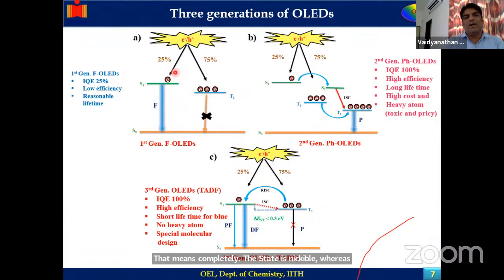That means only one-fourth of the excitons, that is 3 to 1, can come to the ground state by emitting a photon. That means the internal quantum efficiency is restricted to 25%. The efficiency is low, but the lifetime is reasonable. But still, people are using fluorescent material for blue.